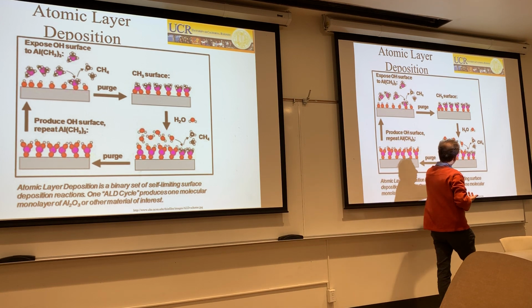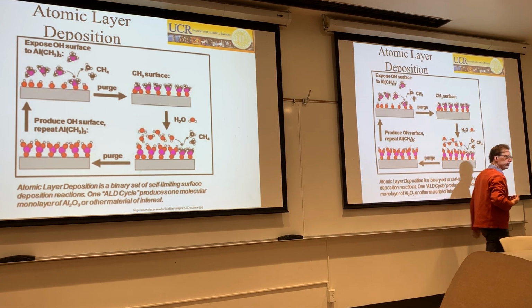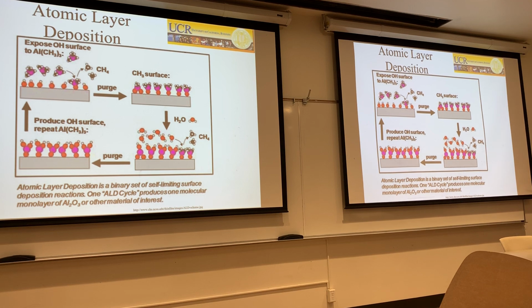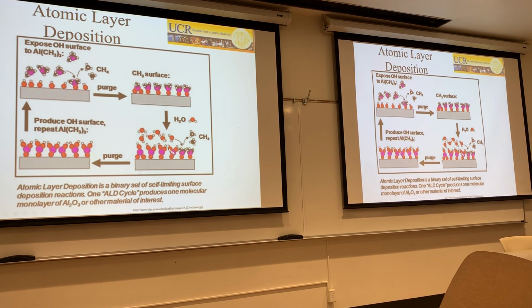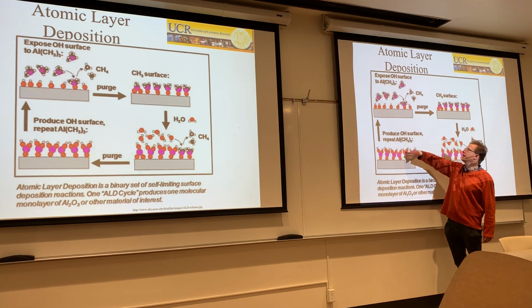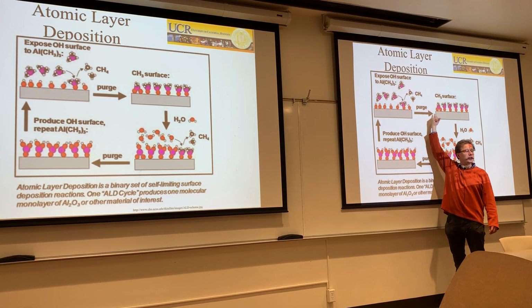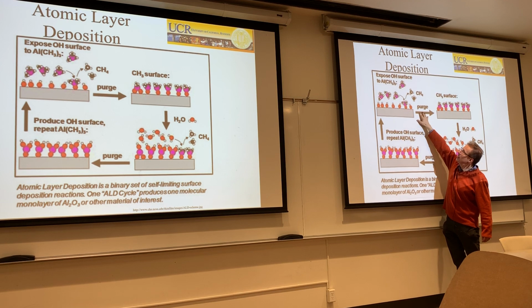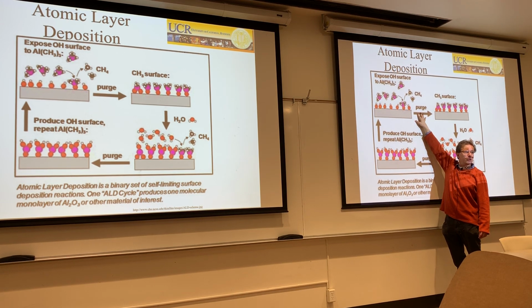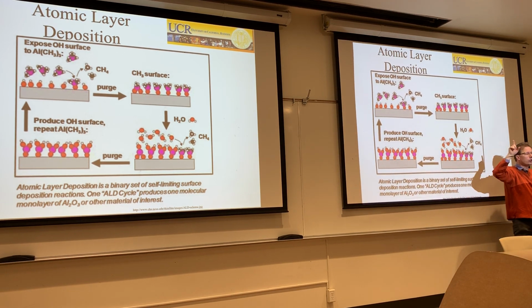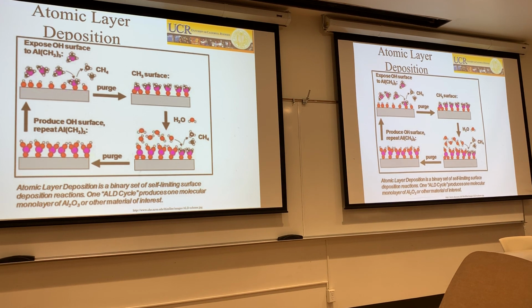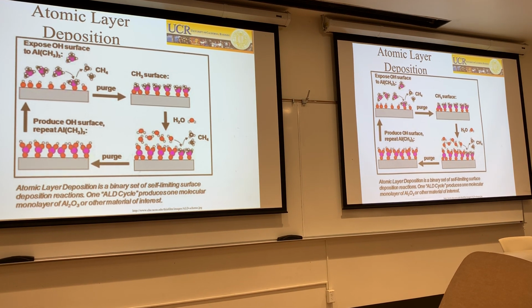Now, in the next step, you expose the whole thing to water vapor, and the water vapor replaces the methyl as methane, coming as OH groups to the aluminum. And then you have again a surface which has those OH groups, so you can start over. Each time you cycle, having either the aluminum precursor or the water in here, you only grow exactly one layer of the material. So you can have layer by layer by layer by layer growth.